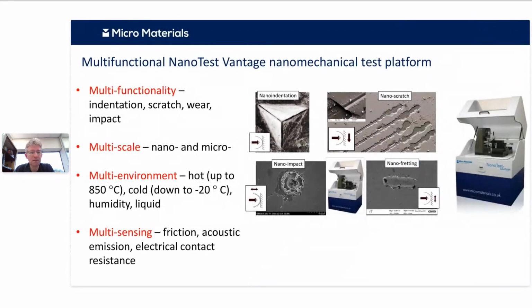So, as I said, the tests are carried out within our Nanotest Vantage, which is a multifunctional nanomechanical test platform. So it has the capability to do indentation, scratch, wear, impact, reciprocating tests, things like that, at nano and micro scales, also in different environments, in hot and cold, and in different liquids or different humidities. And we can combine our tribo testing capability with multi-sensing through monitoring things like the acoustic emission or contact resistance, as well as we measure obviously the friction and the depth in the tests.